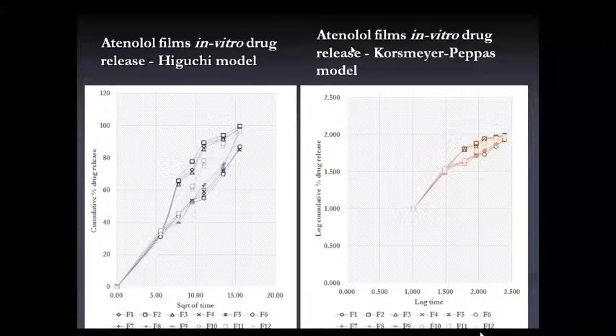By using the square root of time on the x-axis and cumulative percentage drug release on the y-axis, you can get a graph like this. And you can see this graph, the Korsmeyer-Peppas model, which is plotted between log time on the x-axis and log cumulative percentage on the y-axis. By plotting this graph, you can identify whether your drug release is zero order or first order, and also whether the drug release mechanism is Fickian or non-Fickian or carrier transport mechanism. You can identify this from the exponent value n from the graph.